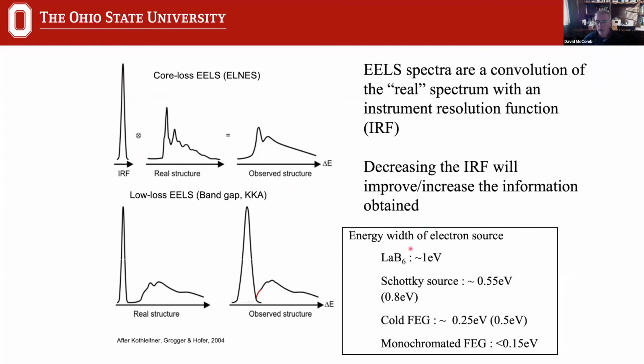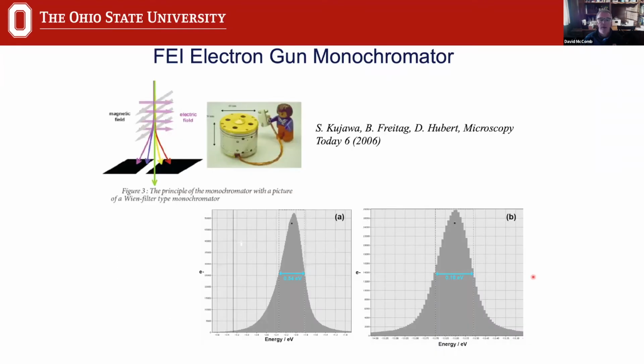And one of the things that we do is make this instrument resolution function narrower and less spread out in energy, then that will basically result in maintaining some more information in the observed structure. And we can do that, for example, by changing the electron source, whether we go from a thermal lanthanum hexaboride source through to a cold field emission source. And then the development that we really saw about 15 years ago or so was the introduction of electron monochromators.